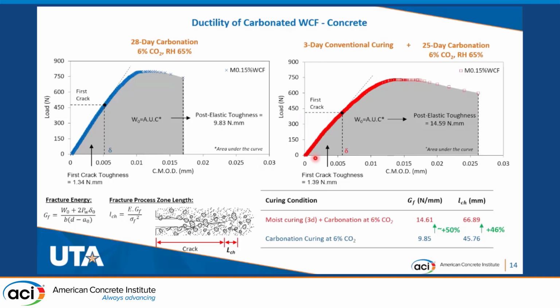We know that because of the formation of calcium carbonates, the brittleness of the cementitious matrix increases. And we conducted fracture mechanics tests to assess the brittleness of the material by evaluating the fracture energy and the fracture process zone length. Interestingly here, immediate carbonation results in a much higher brittleness as suggested by the lower fracture energy and fracture process zone length values, which are observed here in the table.